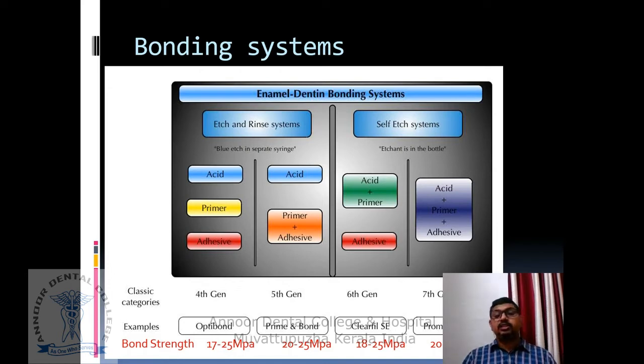You see the bond strength of all these components listed at the bottom. You can see they have bond strength above 18 megapascal. Any dentine bond strength above 18 megapascal is supposed to be satisfactory. That's the advantage of all these currently available systems. The first 3 generations do not reach this bond strength of 18 megapascal. That is why they have been taken off the shelf.